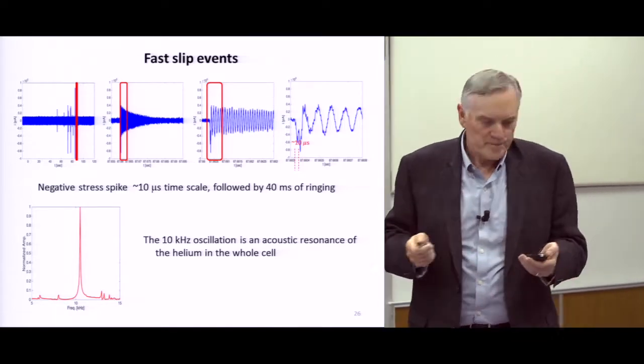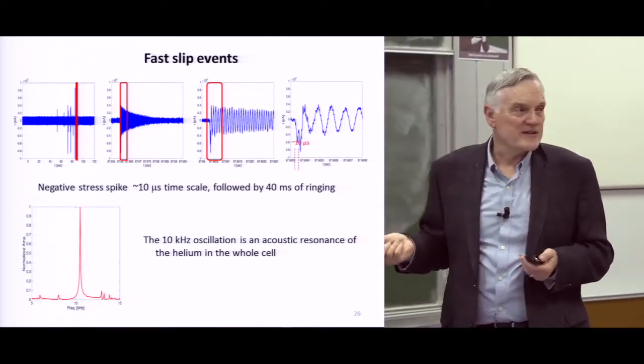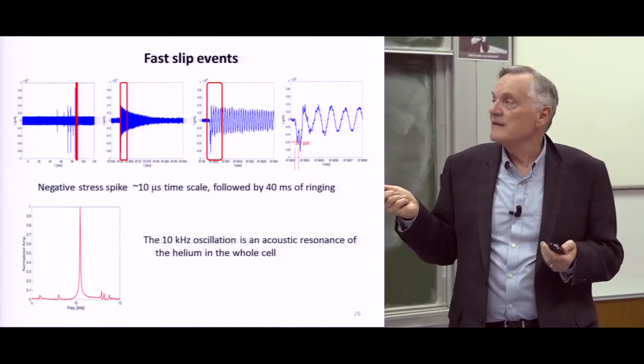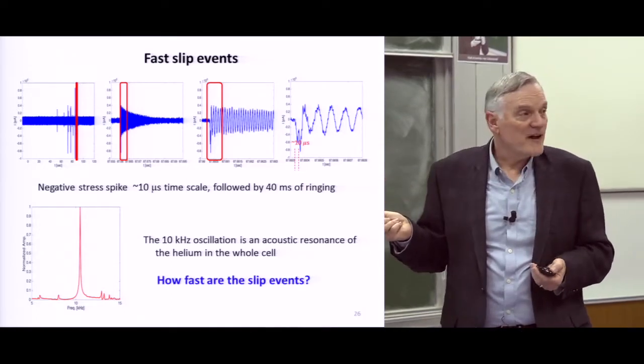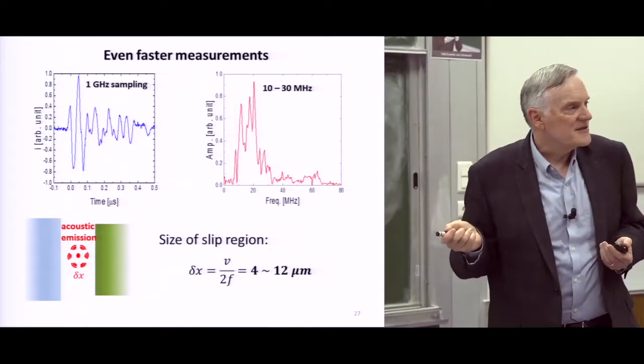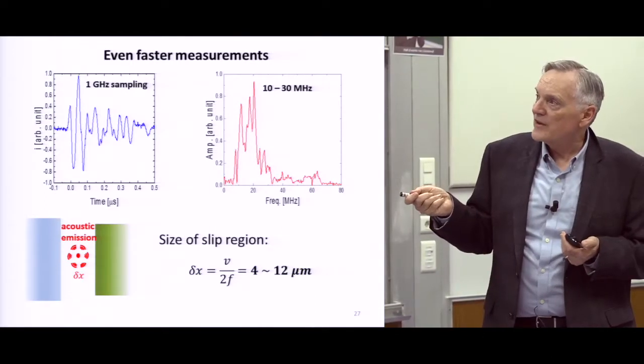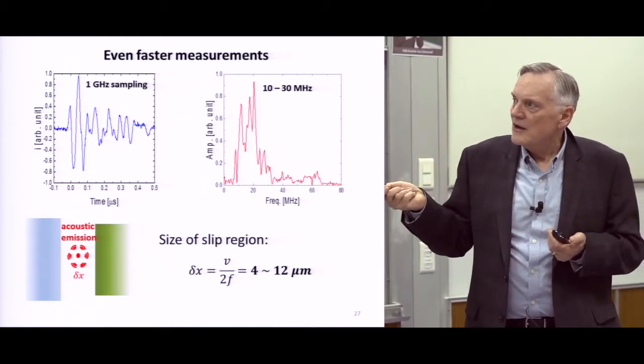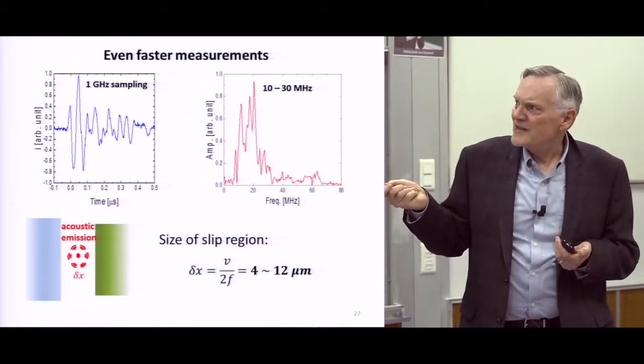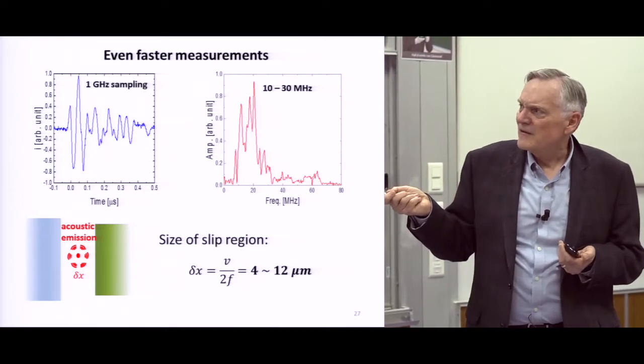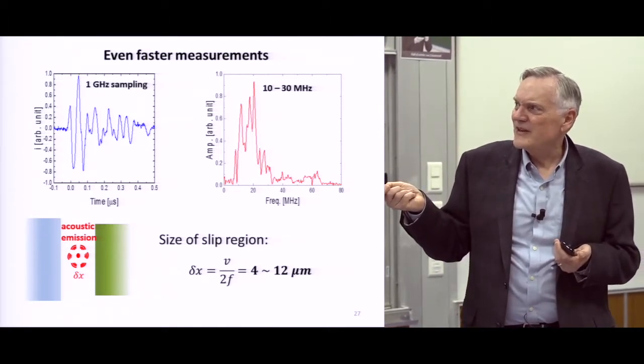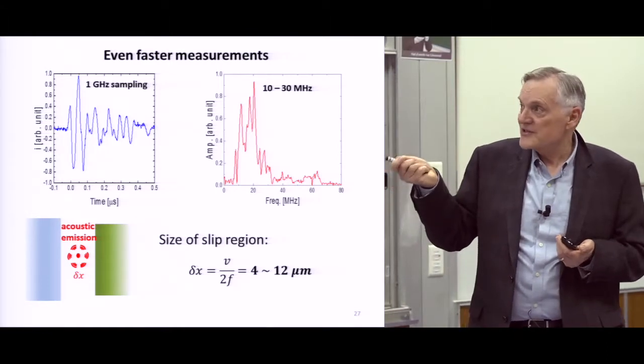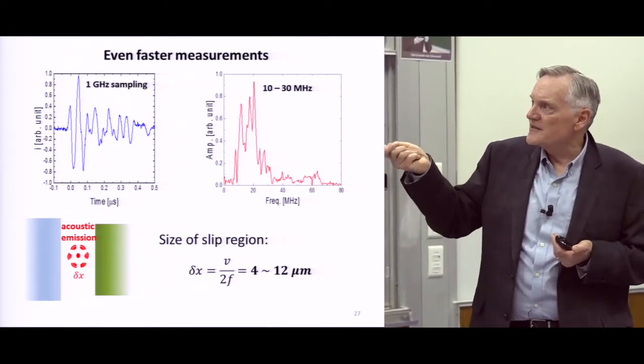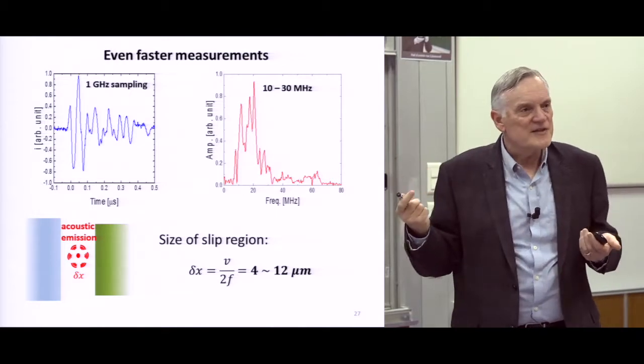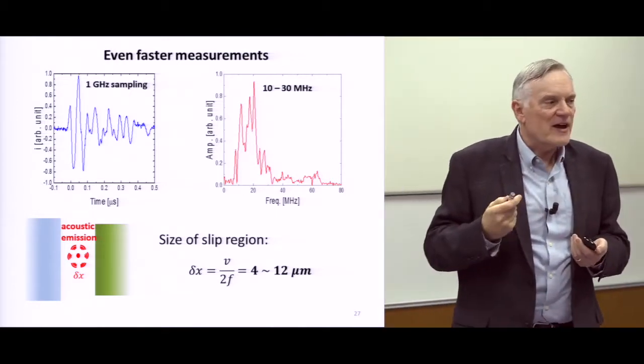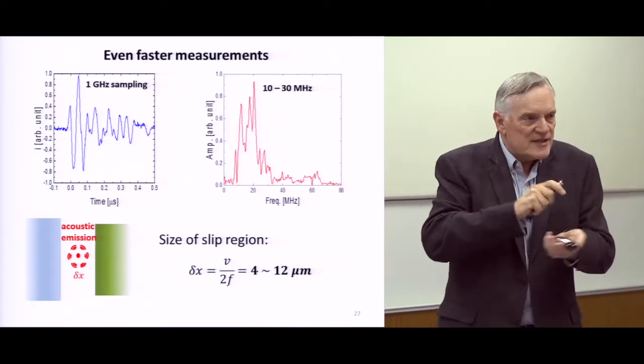So we'd still like to go faster, because this is what we're interested in, and we want to know how fast that is. So we finally put it on a fast digital scope and found that the actual event, forget the ringing later, happens in 40, 50 nanoseconds, the period of this quick part. If you Fourier transform it, it's around 20 megahertz, so 50 nanoseconds is the typical time. So this is a very fast event in helium where the crystal somewhere slips.